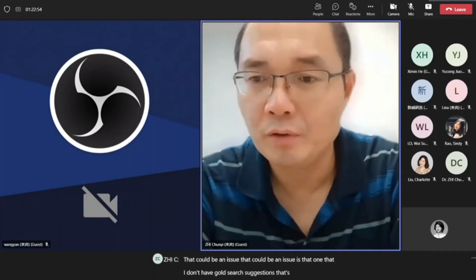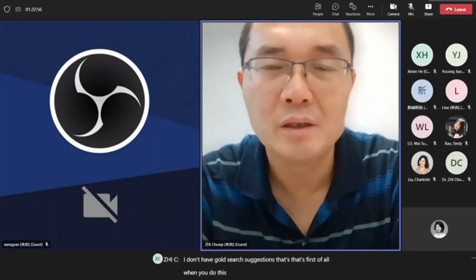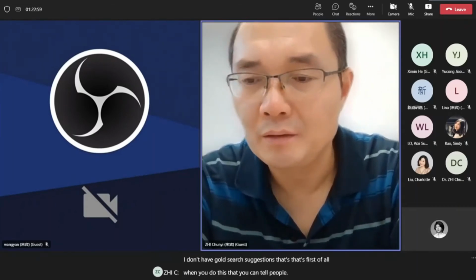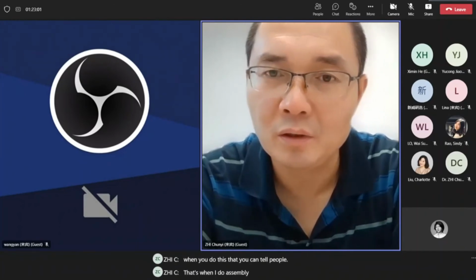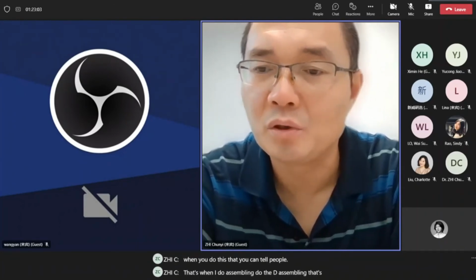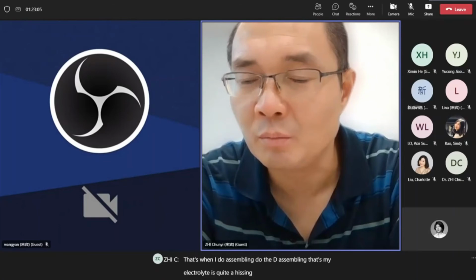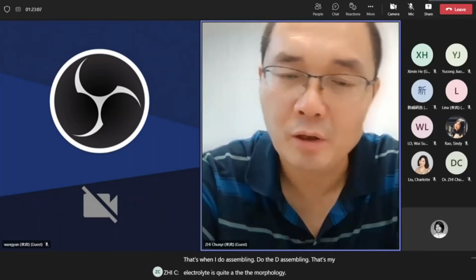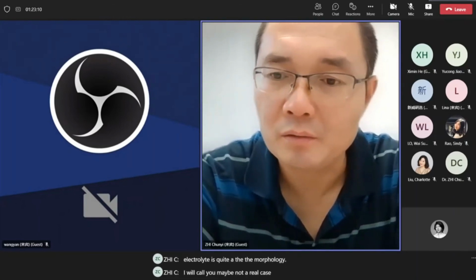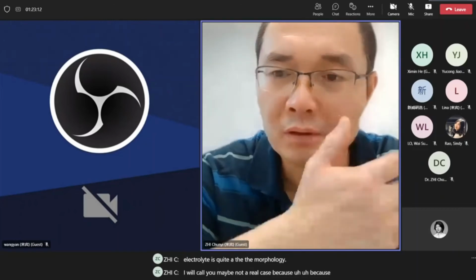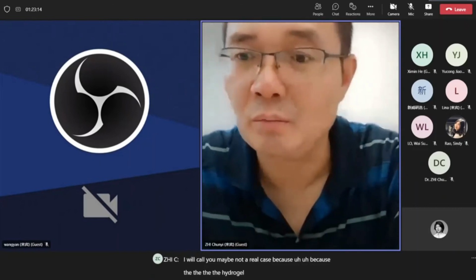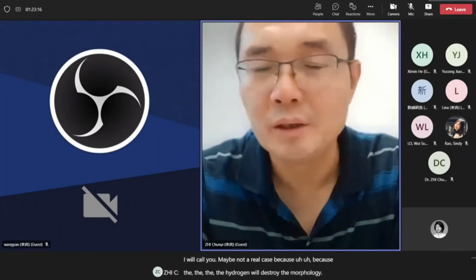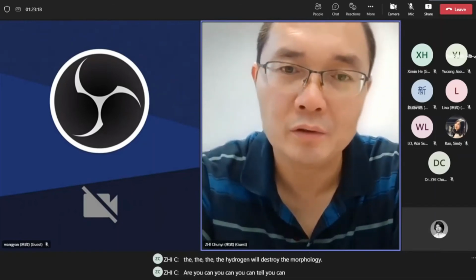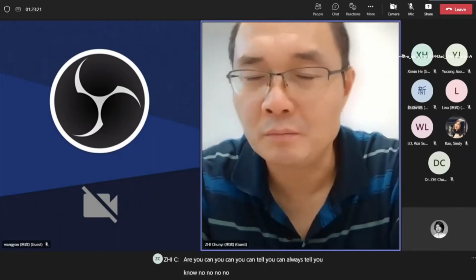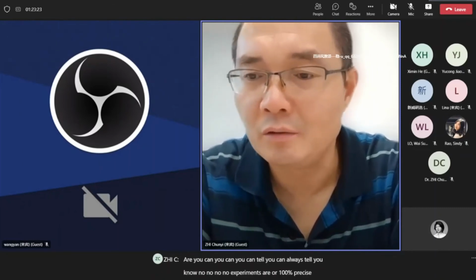First of all, when you do this, you can tell people that when I do assembling and disassembling, my electrolyte is quite adhesive. The morphology I report might not be the real case because the hydrogel will destroy the morphology. You can always tell. No experiments are 100% precise. You can tell your audience, your readers about this.